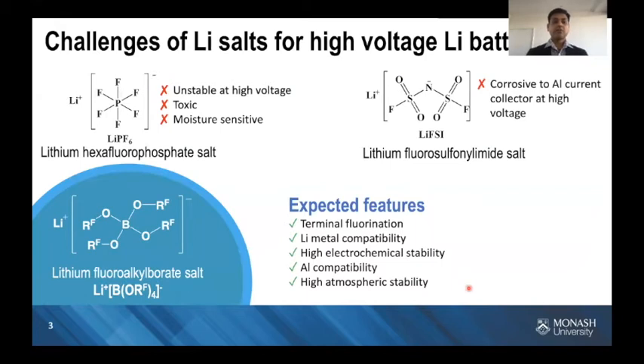When it comes to conventional lithium salts, lithium hexafluorophosphate, or LiPF6, is probably the most well-known one. However, in the presence of high voltage cathodes such as NMC, lithium nickel cobalt manganese oxide, it's known to be quite unstable, not to mention its high toxicity and extreme sensitivity towards moisture, even at the ppm level. The other alternative conventional salt is lithium fluorosulfonyl imide. However, it's also known to show quite prominent aluminum corrosion tendencies, especially at high voltage.